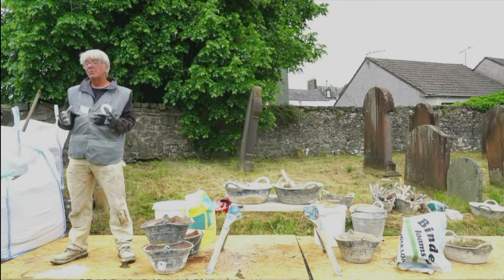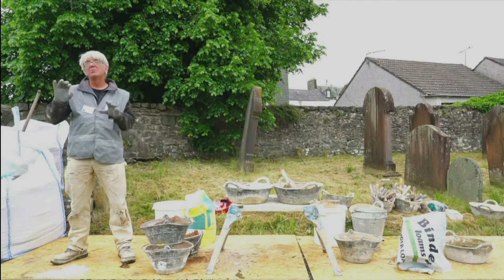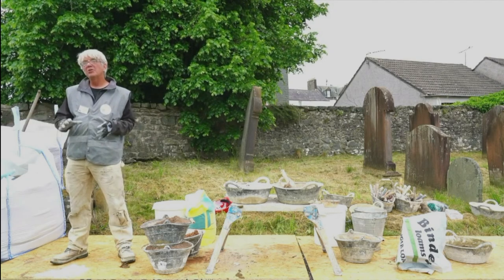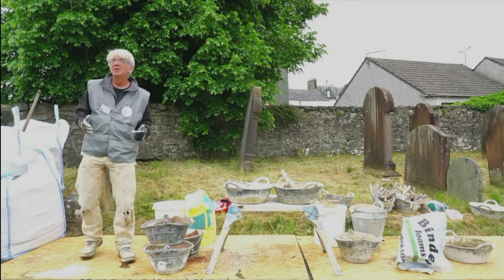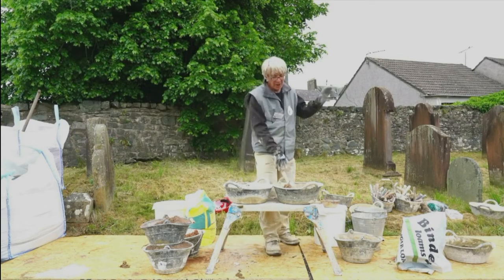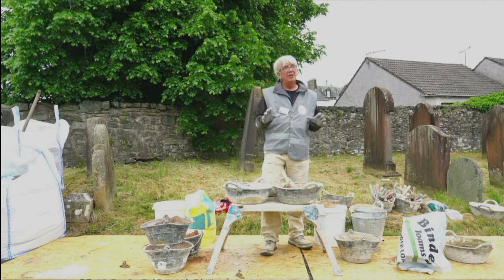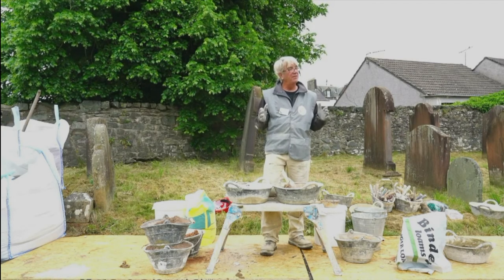But equally, it can be just lime that was never mixed in, that's then carbonated in situ. That's the most common lime lump you'll see, because they know what they want it to feel like. They know when they've got enough lime. They're not going to obsessively try and mix every bit of lime in, necessarily, unless they feel they need to. And those are the things, when you hear about late slaking, it's that underburned or overburned lime, which might slake later. But again, I have to say to you that with pure lime, late slaking is a very rare event.